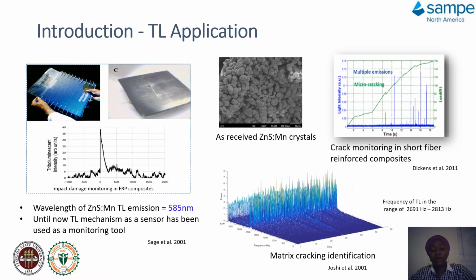And also in 2011, Dickens shows that crack monitoring in short fiber reinforced composite can easily be detected as well. And when you have a short micro crack within the composite, it can easily show multiple emission as the load increases. And this will be able to show the light intensity on the composite without the complete failure of the material. So gradual micro crack within the composite shows emission of light on the surface. And the matrix cracking identification shows that there is a frequency of TL in the range of 2,691 Hz to about 2,813 Hz, as shown by Joshi in 2001 as well.